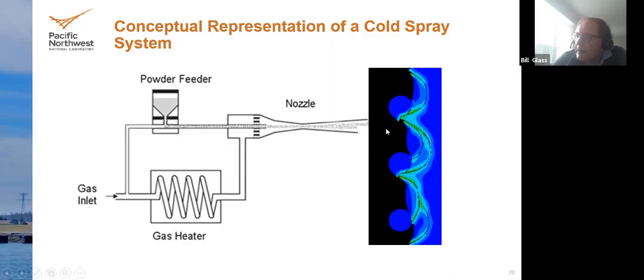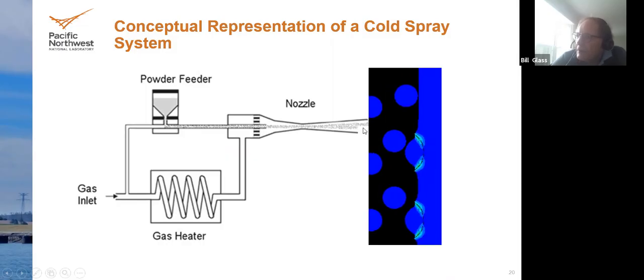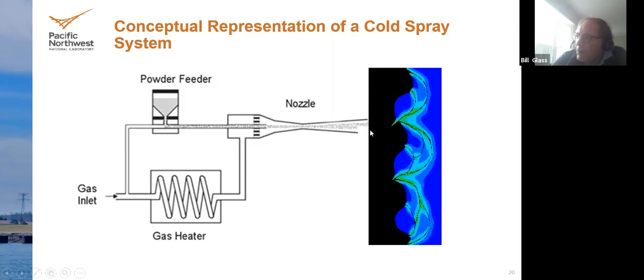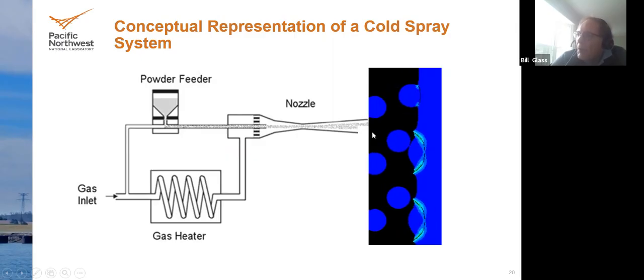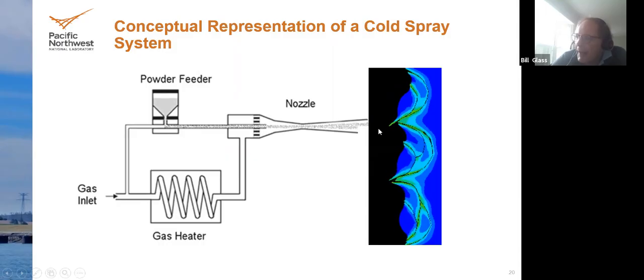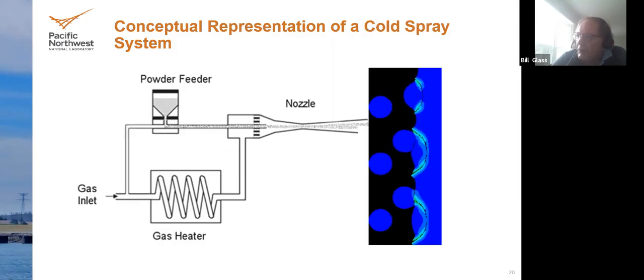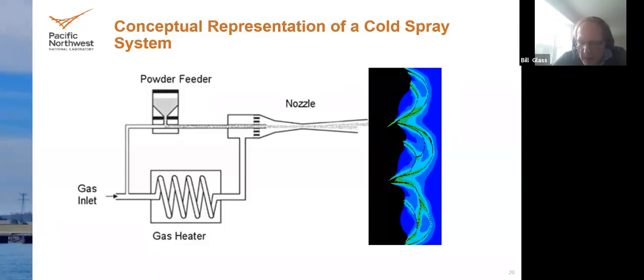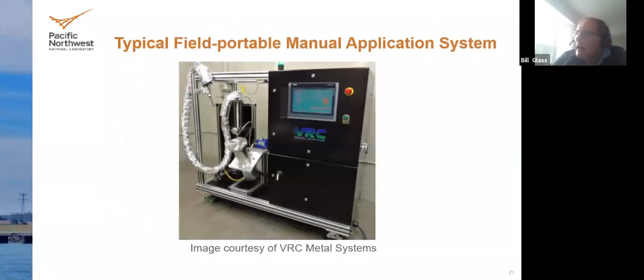They don't get really near the melting temperature of these particles, though. Rather, they form a splat, which is a metallurgically bonded particle to the substrate. You can build up significant layers with this cold spray material. Here is a real picture of a cold spray system like what we have at PNNL, and what you can get to either do factory cold spray work or in the field in situ cold spray work on these systems.